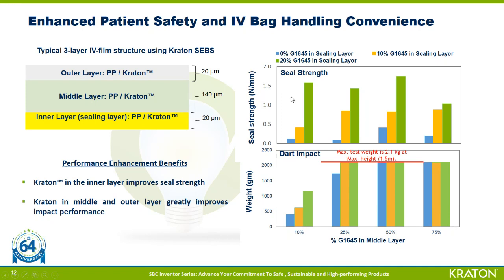So if we now look first at the plot for seal strength, it can be seen that the seal strength increases as the amount of G1645 in the inner sealing layer increases. And you can see this across the entire x-axis, which is the G1645 in middle layer, where it was increased from 10 to 75%. The data on drop dart impact was collected by dropping weights from a height of 1.5 meters. First of all, it can be seen from this data that increasing G1645 in the sealing layer does have a positive impact on drop dart impact resistance of the entire film performance. And you can see that the impact resistance increases systematically with an increase in G1645 in the sealing layer.